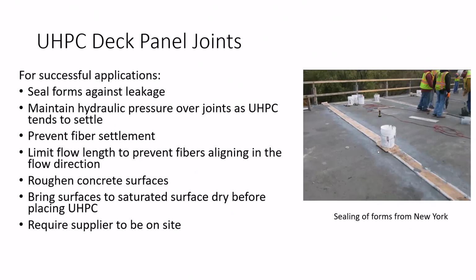Some really key points for making UHPC work, and this is not just for these two applications discussed, but for really any application of UHPC. One very important thing is to really seal the forms against leakage, because UHPC is a lot more flowable than normal concrete. That is why you see on that right side there is actually a top cover for the form. And the material tends to settle a little bit when it hardens, so you actually have to fill the joints a little bit more than you need to account for that settlement. That's why you see that bucket here. It's maintaining that hydraulic pressure over that joint, and if you have a little bit extra, then you can just grind it off later.